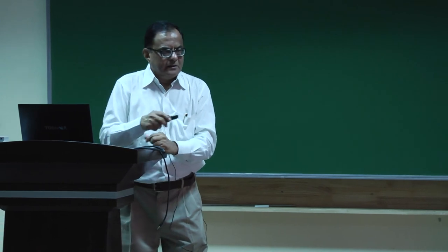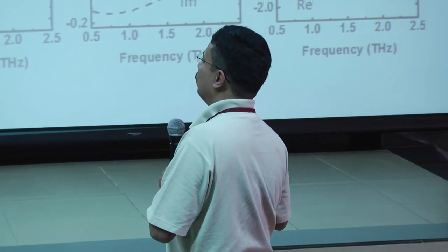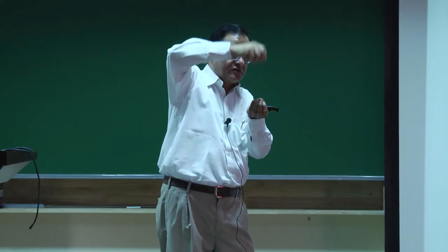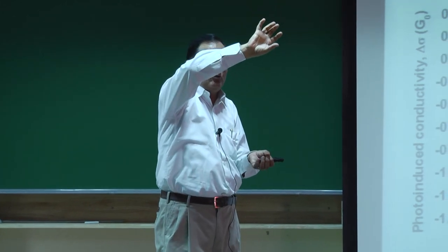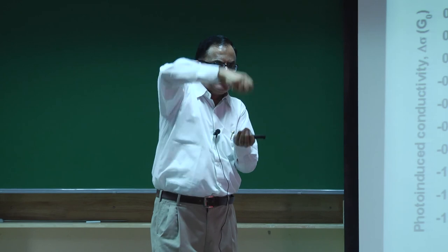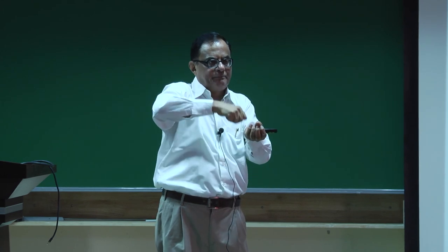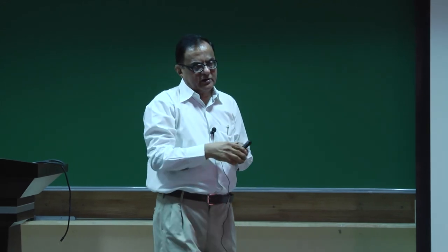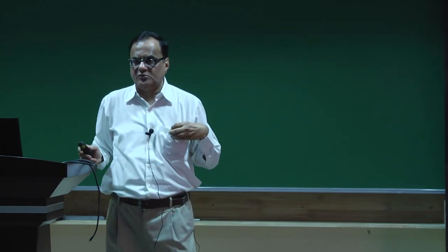[Question]: Did you do a fluence dependence in graphene? Do you see effects of Pauli blocking? [Answer]: I didn't show it. We are looking at intra-band transitions here. Inter-band transitions would be affected by Pauli blocking, but our pump is at 1.5 eV while the THz probe is only probing intra-band processes. If you do pump-probe where the probe is at the same wavelength as the pump, then Pauli blocking would block probe absorption — but that's not what we do here.